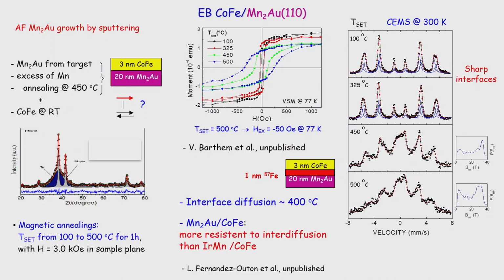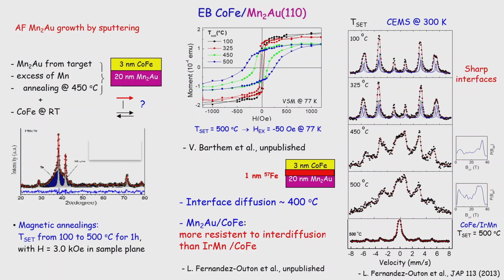That means this is the temperature where we start to see interdiffusion at the interface. But if you compare with the system with iridium manganese, that is the standard antiferromagnet for applications, we see this one is much more resistant to diffusion than iridium manganese. We didn't publish this yet, but these are interesting results.